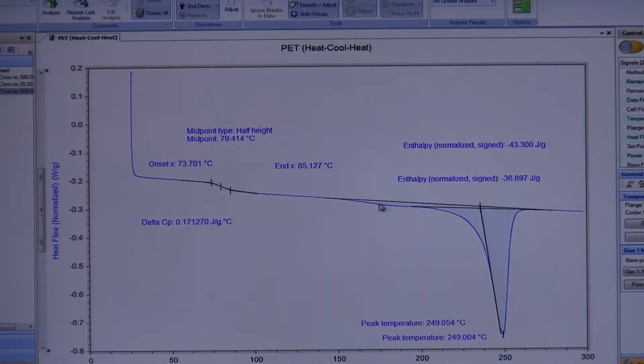Typically, when you see things like this, you definitely want to ask yourself what part of this is attributed to the melting curve and what part might be something different. In this case, this is actually part of your melting curve. And if you look at certain equations in thermodynamics, you would see that as your crystals get smaller, the melting transition also gets smaller. So the temperature at which you melt the crystals is lower for smaller crystals.